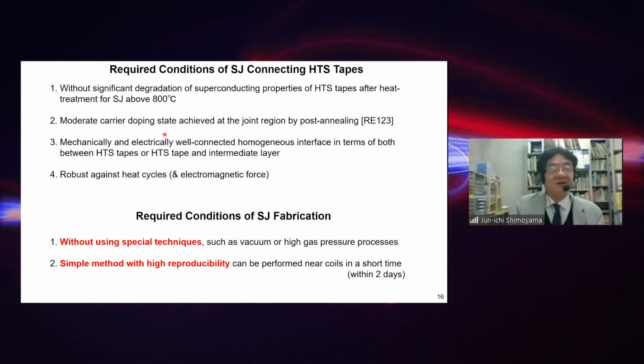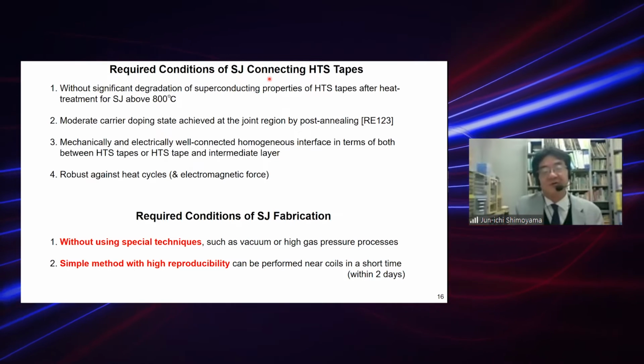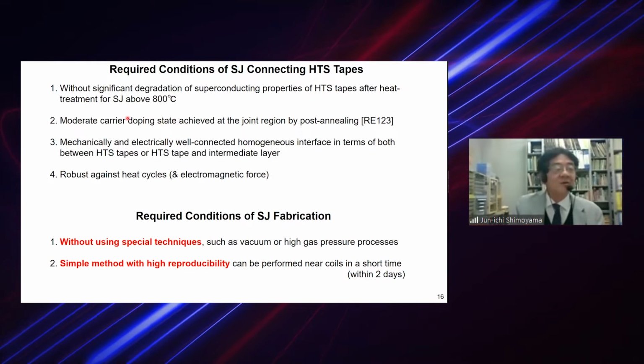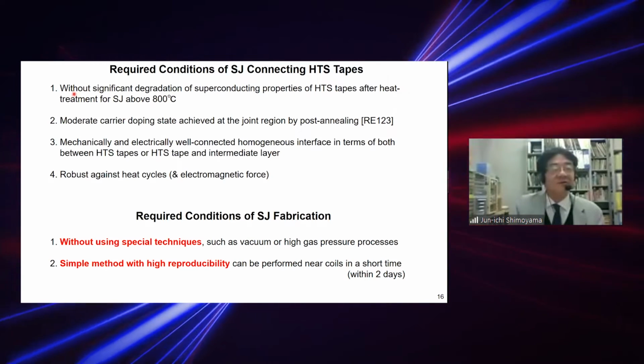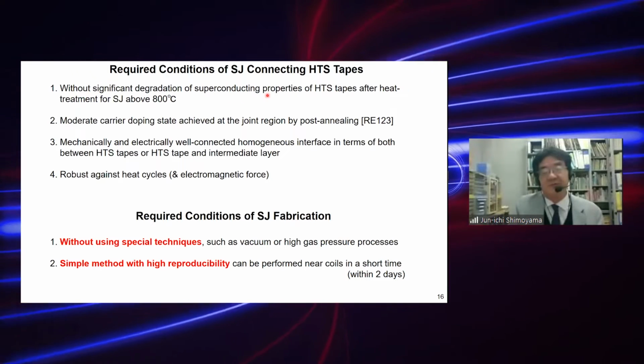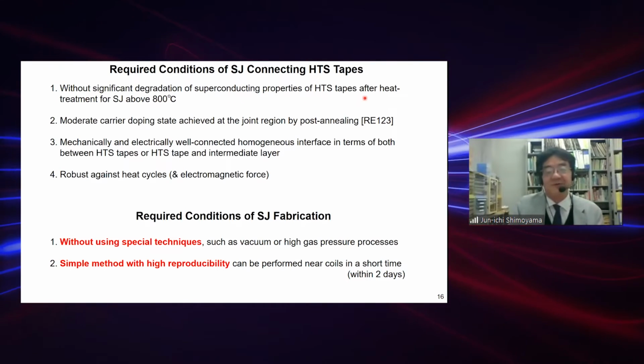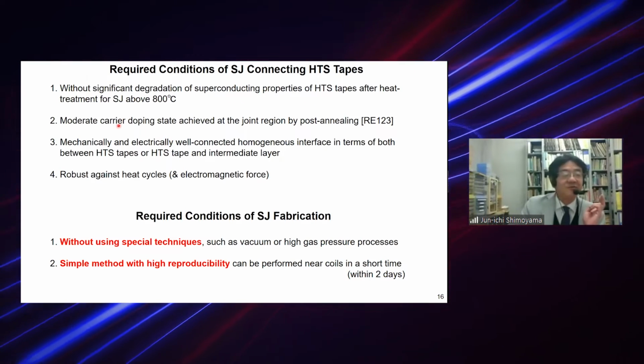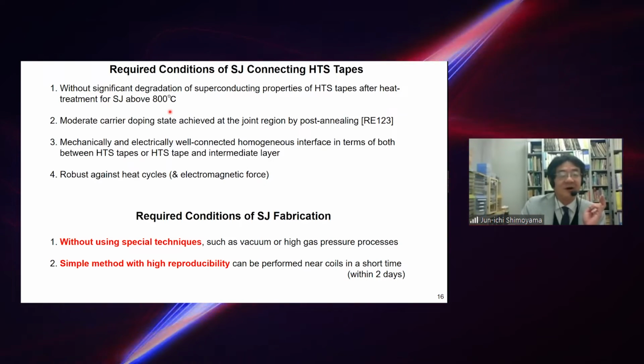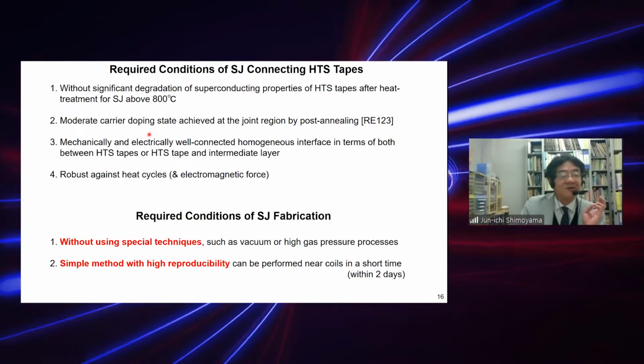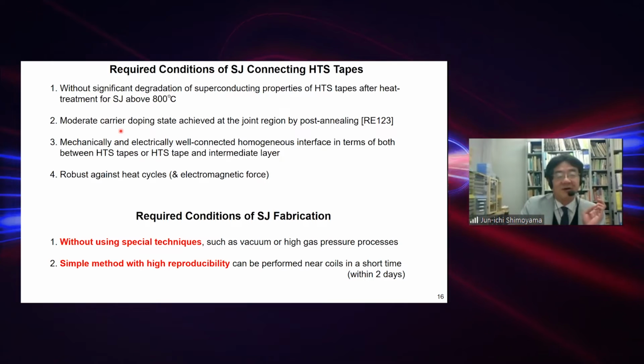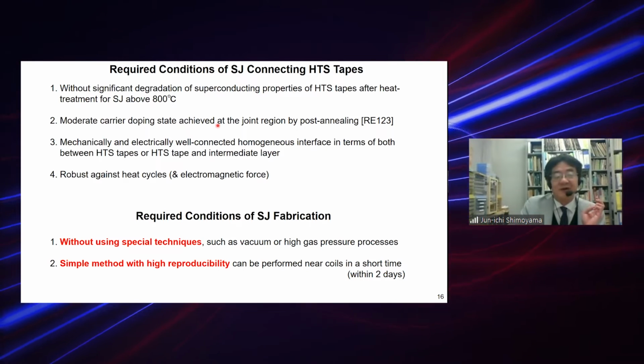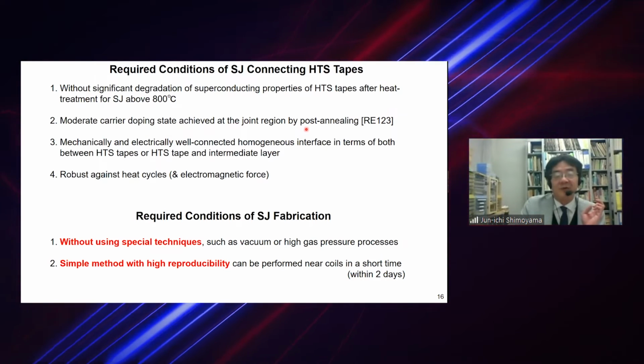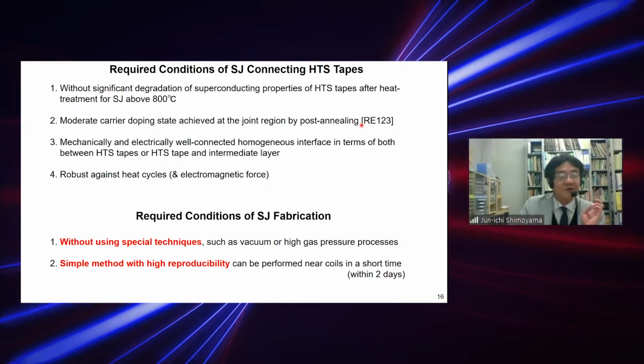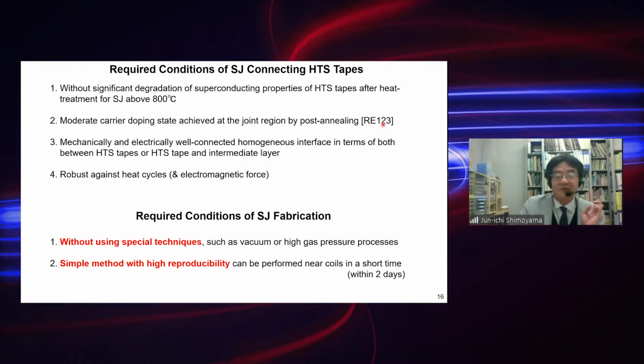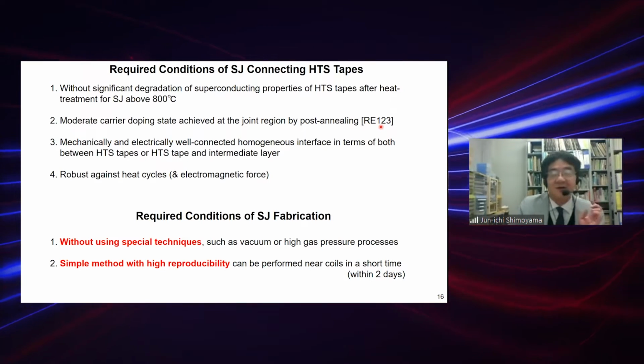So here I listed the required conditions of a superconducting joint connecting HTS tapes. At first, the HTS tapes must not show significant degradation of superconducting properties after heat treatment for the superconducting joint above 800 degrees C. And second, a moderate carrier doping state must be achieved in the joint region by post-annealing. This is a very important point for RE123 systems, as I discuss later.